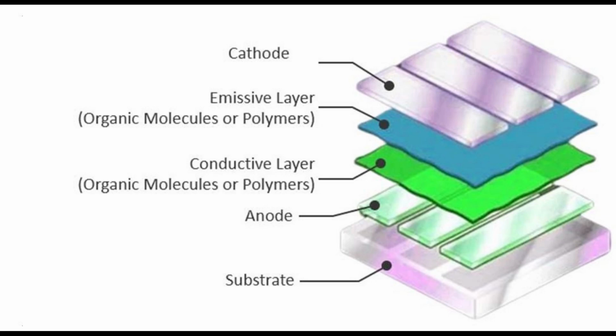It was found that the introduction of two carbazole units into the same benzene ring of the oxygen-bridged triphenylboron electron acceptor unit could effectively suppress the conformational relaxation of the molecule during the radiative transition, resulting in narrow bandwidth blue light emission. In addition, TDBACZ is the first reported blue material to achieve both a FWHM down to 45 nanometers and a maximum EQE of 21.4% in a non-doped TADF OLED.